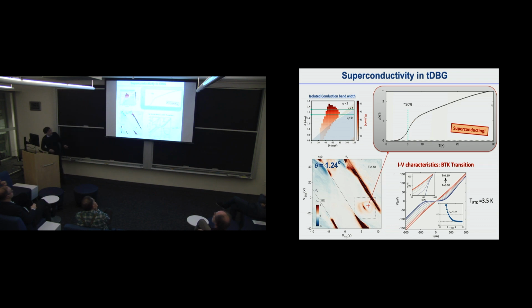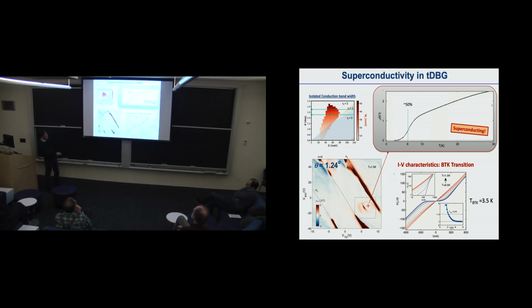But the huge difference here is that when you dope this correlated insulating state, we actually get superconductivity, and this superconductivity is rather robust. You can measure the transition temperature at around 6 Kelvin, or more quantitatively at the 50% point. You can measure the BTK transition via the IV curve, and from there extract the KT transition temperature, which gives something like 3 Kelvin. So there's a rather robust superconductivity appearing here.